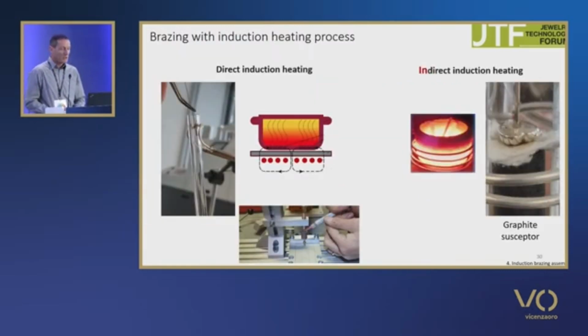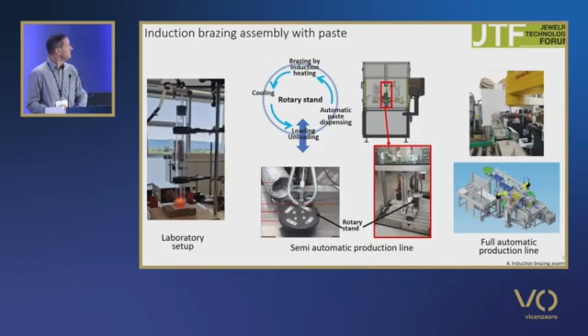There are two ways of induction. Direct induction heating, where you put the components closest to the induction coil, or indirect heating, where mainly you use a graphite susceptor. In a production line, the basic setup starts from the laboratory setup. You can fully manage the equipment with a semi-automatic process, mainly based on a rotary stand, and sometimes a fully automatic process with a belt conveyor.